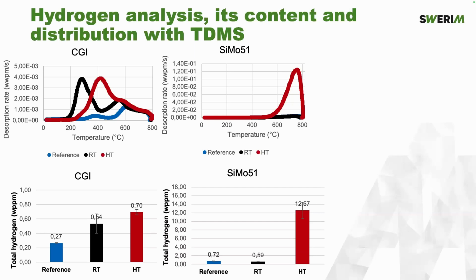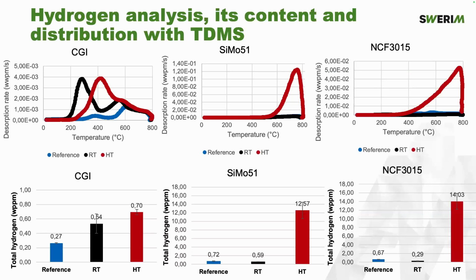CGI, not high effect on room temperature in terms of uptake. So the curves quite match with the reference measurement. On the other side, we have the high temperature where we do see an uptake, and that is, of course, expected. As well, the same, similar to NCF material. So, namely, the high temperature test resulted in only strongly trapped hydrogen uptake.